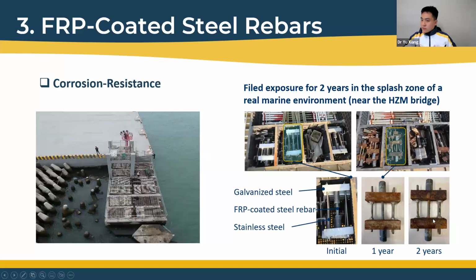After 2 years of exposure in the marine environment, the galvanized steel corroded seriously, and the stainless steel also exhibited pitting corrosion. But the FRP coated steel rebar was still in a very good state, even when we cut it to check the cross section.